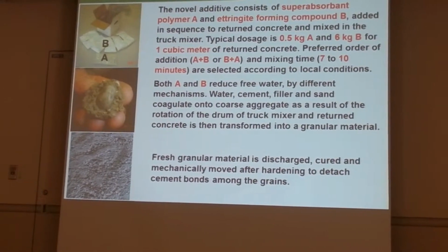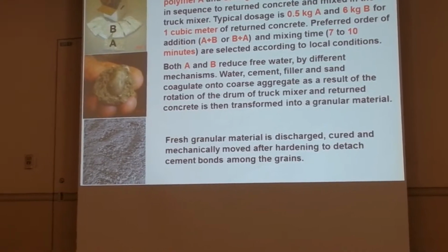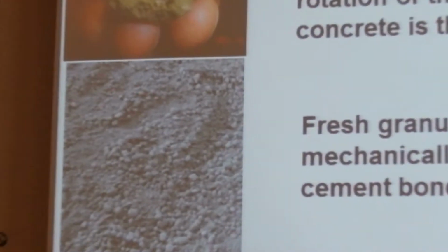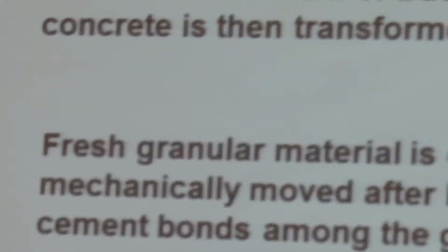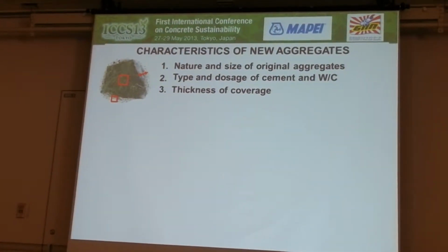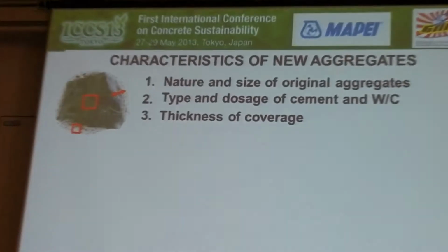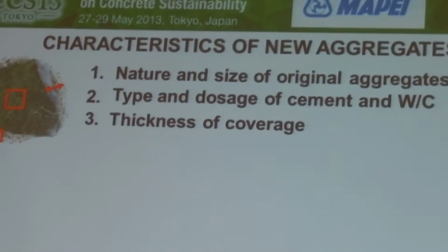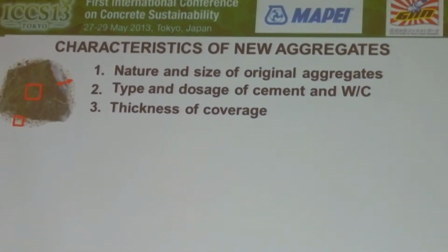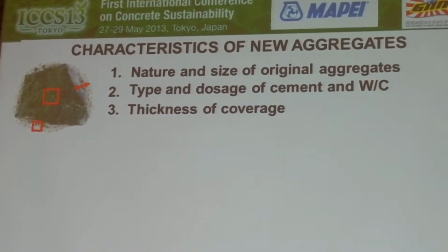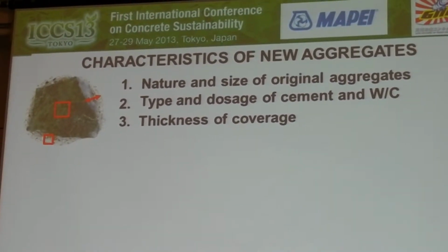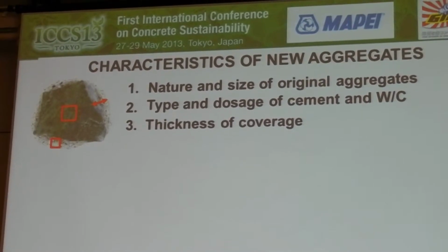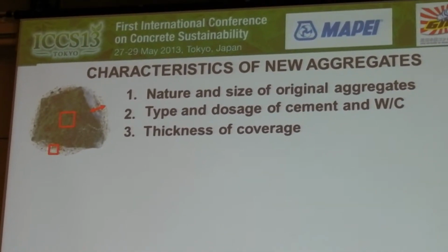After that, the material is discharged on the ground and left to harden as a normal cementitious material. And the day after, it is gently moved by an excavator in order to detach the individual grains, giving again the final aggregate. Once the aggregates are obtained, they can be reused after some days for the production of new concrete. Of course, the characteristics of the new aggregate depend on the nature and size of the original aggregates, the type and dosage of cement and the water to cement ratio, and the thickness of the coverage.